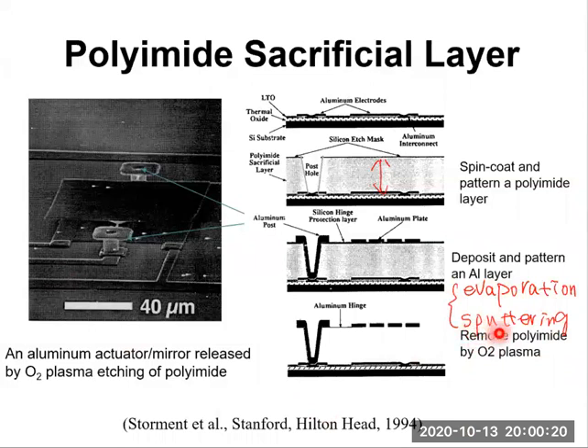Because sputtering provides better step coverage. That's what we learned in chapter 5 or chapter 6, in the previous two chapters, where we studied evaporation and sputtering. Evaporation is a line of sight deposition, so it has a poor step coverage. And the sputtering, because of its much shorter mean free path, has a better step coverage. So here it's better to use sputtering because we want to cover this post hole. We want aluminum to be deposited along this almost vertical side wall.